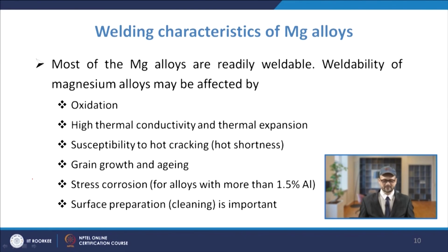It has very high thermal conductivity and also high thermal expansion, and because of that there is a challenge in the welding of magnesium, because large residual stresses may form, which may lead to distortion of the component. So precautions are taken: you go for fast welding speeds, smaller welding beads, holding the parts in a jig, and use of lower melting point, lower shrinkage welding rods. These points are effective in controlling distortion.